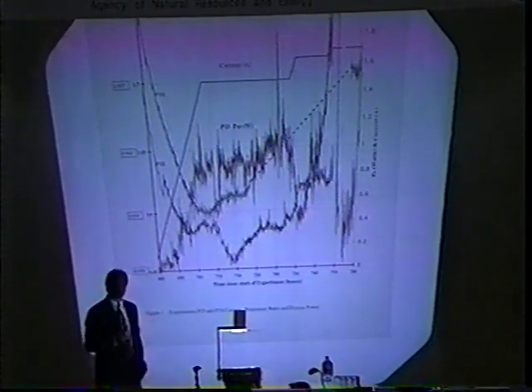And as the current increased, the loading increased, the resistance ratio came down, and this really attained a very remarkable level of loading, a loading of 0.97. Good, but better than that, it maintained the loading for substantial periods of time, many days, while the current was held at 1.5 amps. This is the sort of behavior that we're hoping to achieve.